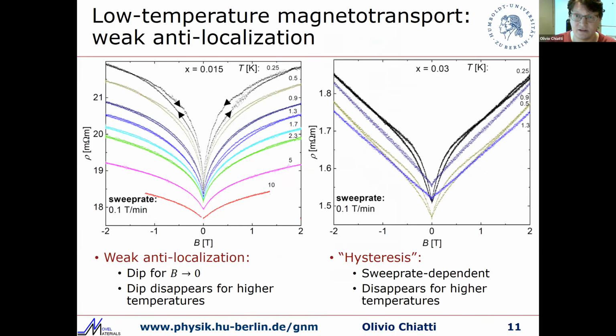So the magnetotransport at low temperatures shows dips in the magnetoresistance around zero field. And we see that these dips are consistent with weak anti-localization. So the topological surface states are still spin-momentum locked, like we expect in a normal topological insulator. And we can see that the dip disappears if we increase the temperature. So at 10 Kelvin, the dip is not sharp anymore, but it's around here.